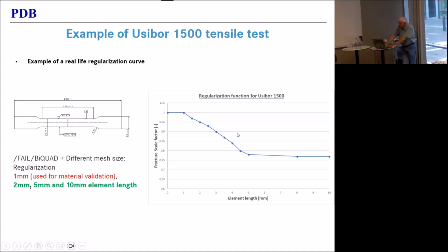So we did an example on Usibor 1500. We modeled a typical tensile test. Marian generated a biquad failure criterion and determined a regularization curve, which is basically a scale factor applied to the failure curve, where the failure curve is a function of triaxiality. And you see that that scale factor is 1 for a mesh length of 1, which happened to be the mesh size for which the material model was validated. And then as the mesh size becomes larger, we have to bring that scale factor down. And as you can see, we don't have to bring it down by just a little bit. It goes down by about 30% in this moderately severe example.